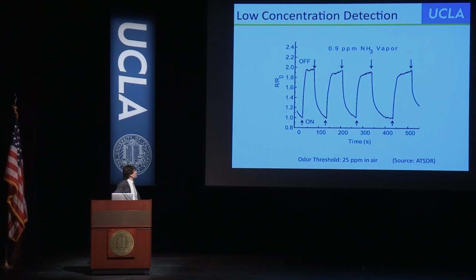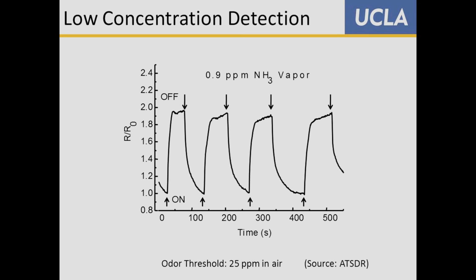And you can see this, you can do it with acid in the de-doped form, or you can take the doped form and bring up base. Here we're bringing up ammonia, we turn it on, the resistance goes up, we turn it off, and it's reversible. And this we're doing less than 1 part per million of ammonia. Now, you know your nose is very sensitive to ammonia, but even the best nose cuts out at about 25 parts per million in air. So you could not smell this.